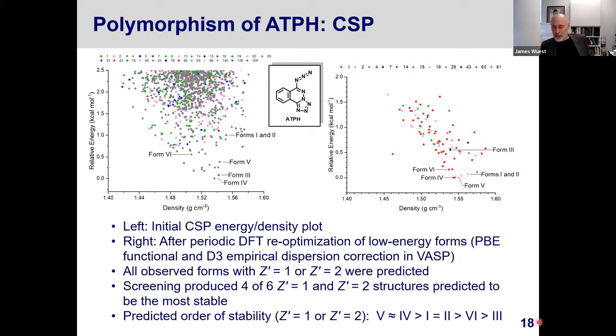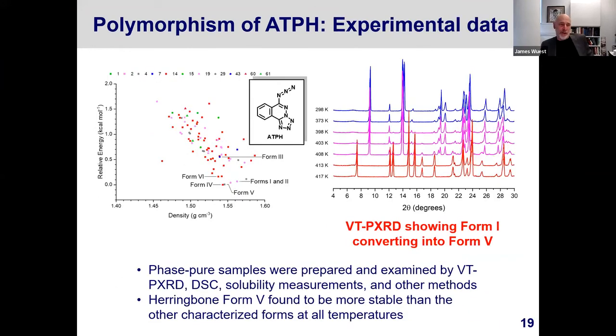And so we were able to develop conditions that produced all of the forms in essentially phase pure forms. So we were able to characterize them by all the different available techniques and carried out various experiments to compare their stabilities. And basically form 5 turns out to be the most stable, slightly more stable than form 4.